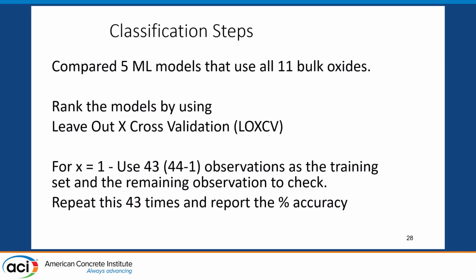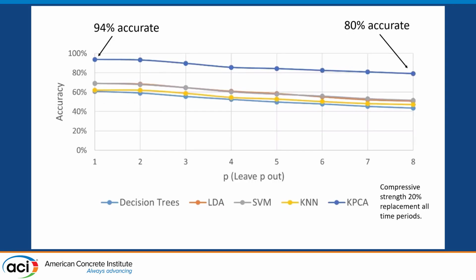Well, we didn't just use 1. We went all the way up to 8. So if you randomly choose 8 data sets out and apply that, that's a lot of measurements, that's a lot of validation, that's a lot of looking. So what I'm talking about is this. Here are 5 models. Here's if I leave 1 out. Some of these did okay, but this one did really well, 94% accuracy. Okay? And over time, obviously, as you leave more out, you take more of the raw measurements out and test it more, it's not going to do as well, but it's still at 80% accuracy. It's not like it tanked to nothing. Does that make sense what I'm saying to everybody? That looks at the robustness of the model that you're actually looking at.